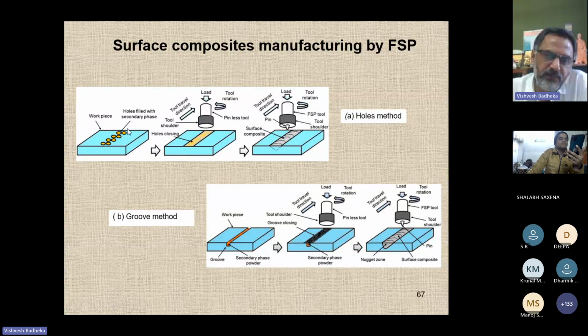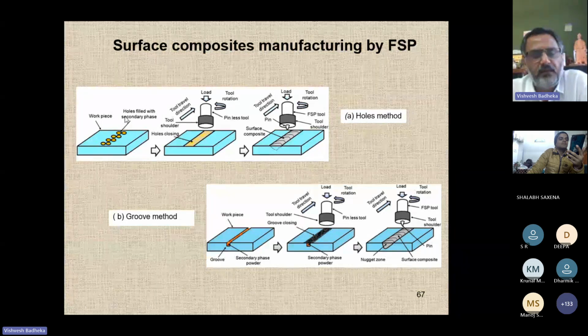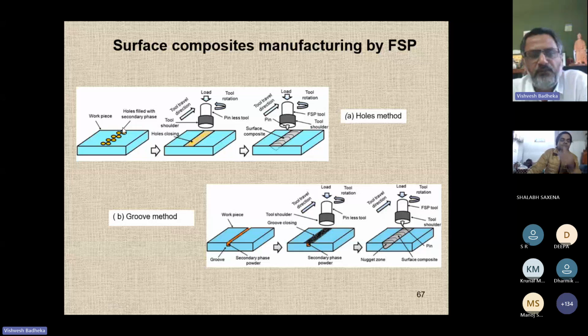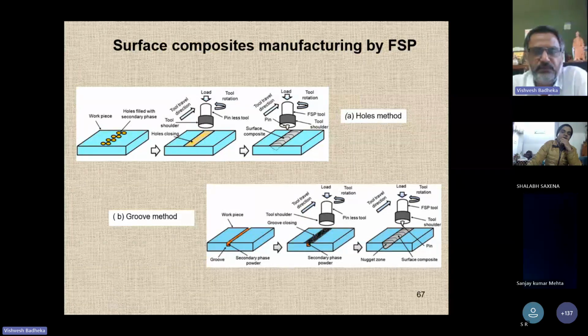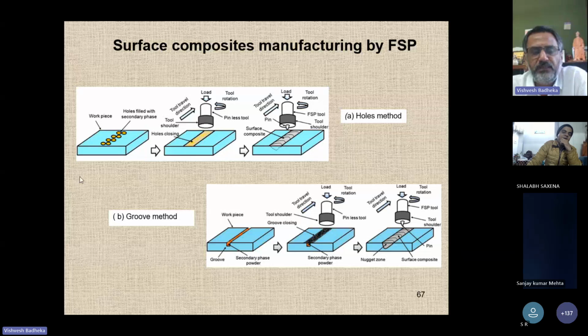Then you develop blind holes of a certain diameter and certain depth under the pin region, and then you fill those holes with reinforcement, for example boron carbide. Because boron carbide is a dry powder, it is very difficult to fill these holes with dry powder. So you need to mix it with some carrier solvent. You can use acetone and make a small slurry, and the slurry will be filled inside these holes.